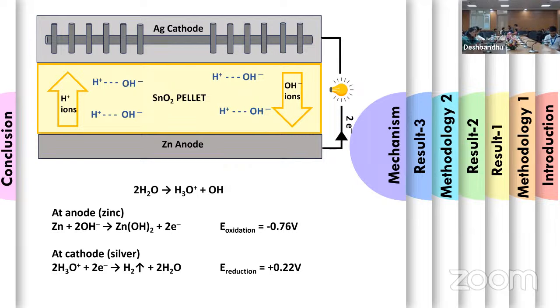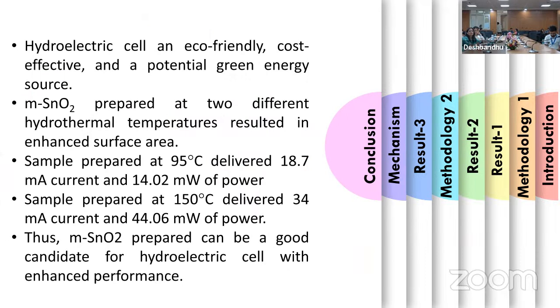So it is pretty evident from the reaction itself that the byproducts formed here are environment friendly, and this is an eco-friendly alternate source of energy. In conclusion, the hydroelectric cell is an eco-friendly, cost-effective and potential green energy source. Mesoporous tin oxide prepared at 2 different temperatures resulted in enhanced surface area, and the cell prepared at 150 degrees Celsius showed better properties compared to the low temperature. So the mesoporous tin oxide prepared can be a good candidate for the hydroelectric cell.